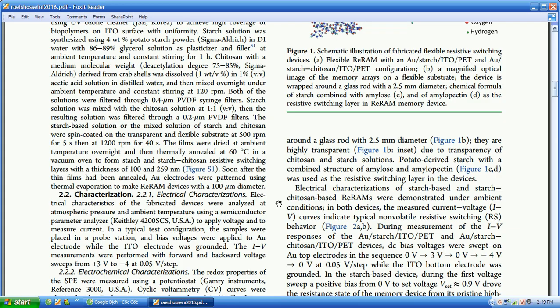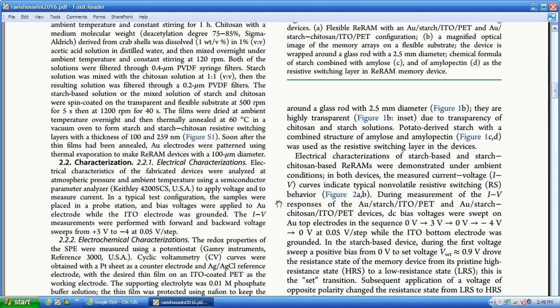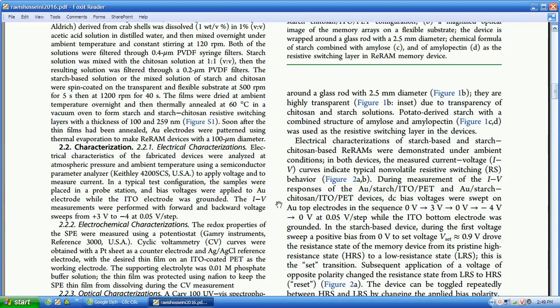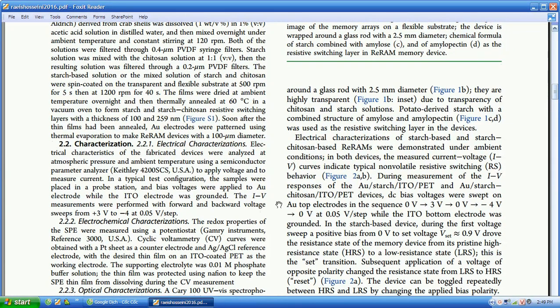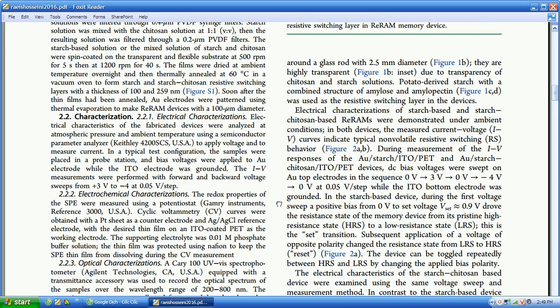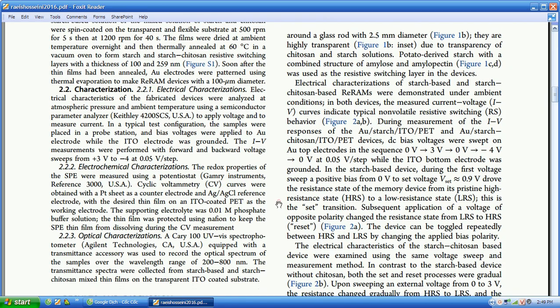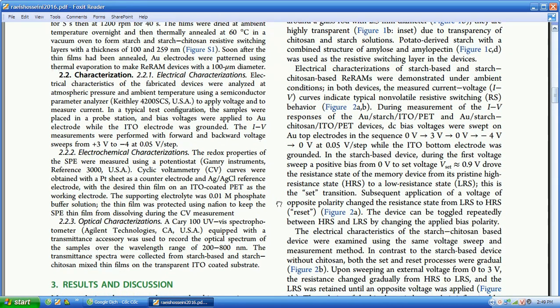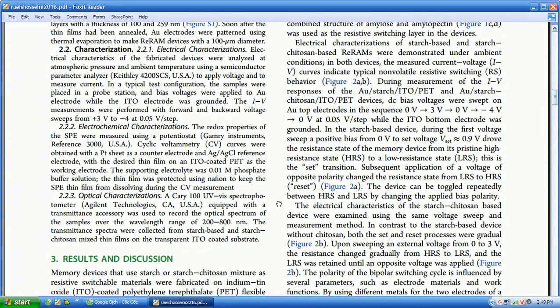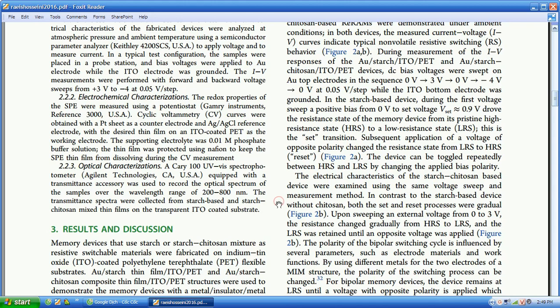Potato-derived starch with a combined structure of amylose and amylopectin, figure 1c, was used as the resistive switching layer in the devices. Electrical characterizations of starch-based and starch-chitosan-based ReRAMs were demonstrated under ambient conditions. In both devices, the measured current-voltage, I-V, curves indicate typical non-volatile resistive switching, RS, behavior, figure 2a. During measurement of I-V responses of the Au/starch/ITO/PET and Au/starch-chitosan/ITO/PET devices, DC bias voltages were swept on Au top electrodes in the sequence 0 to 3 V to 0 to -4 V to 0 at 0.05 V/step while the ITO bottom electrode was grounded.